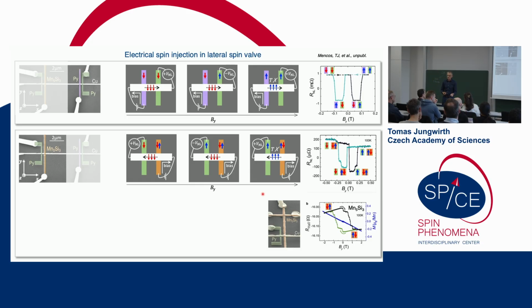An external magnetic field can couple to the weak magnetization, the relativistic one, and the weak magnetization tends to be coupled to the Néel order by, for example, DMI or some relativistic terms that couple the Néel vector and the weak magnetization. So the idea is that the external magnetic field couples to the magnetization and switches it, and then the magnetization is coupled to the Néel vector, so it switches the Néel vector also. And this is how it's controlled in all these experiments on manganese telluride or in all the other altermagnets, when you can control the sign of the order by magnetic field.